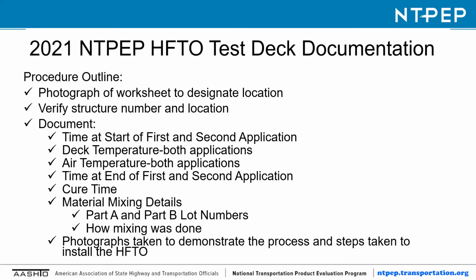We do know that these products, these binders, cure within an hour or two after placement. And some of the times the contractor would leave, go to another test deck, come back and later sweep off. That doesn't mean when he came back and swept off 3 or 4 hours later, it took that long to cure. Most of these are traffic turned on them within 2 hours and sometimes sooner. I don't recommend it, but some of them are faster than that.